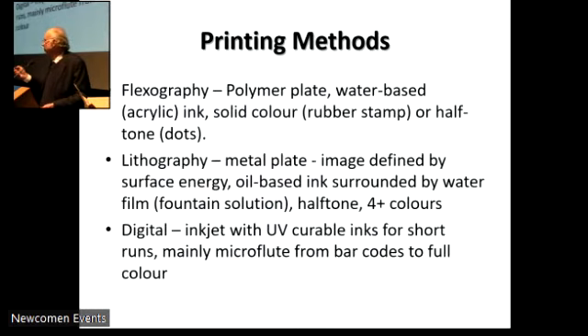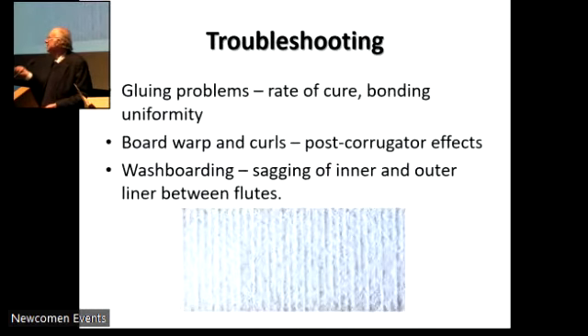And this, as we see in the picture, is the sagging of the inner or the outer liner between the flutes. So most corrugated containers have that to a limited extent. Now, you can tolerate a little bit on the inside because nobody's going to look at the inside of a corrugated container. It is no good if you're printing on it, though, because there may be areas in the wells or recesses between the flutes which don't pick up the printing ink, and you get a lousy image. And for that reason, amongst others, the outer liner is normally of heavier weight and of smoother surface than the inner one.